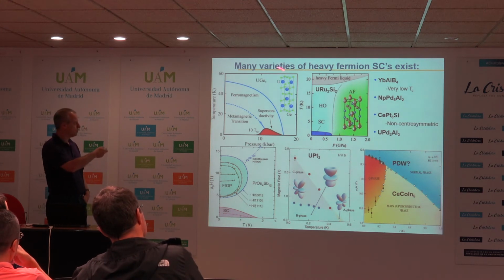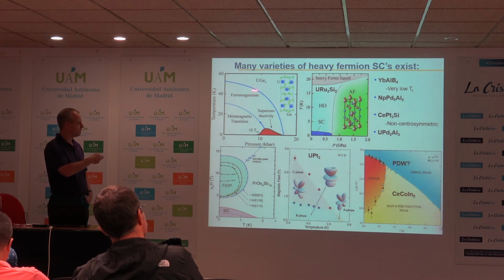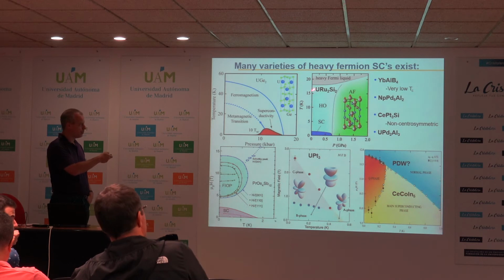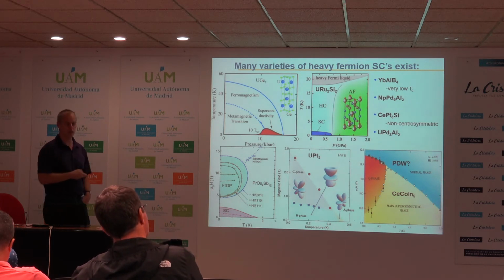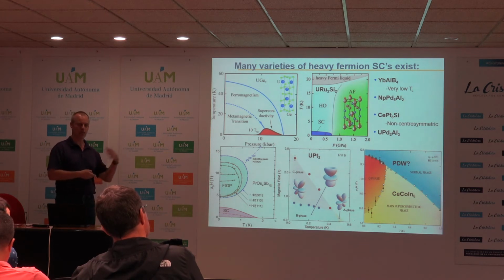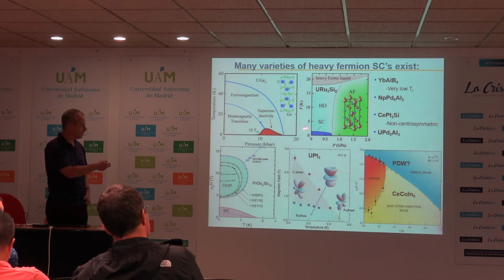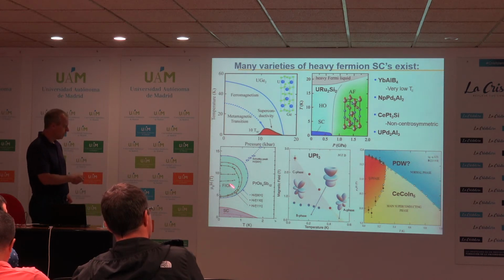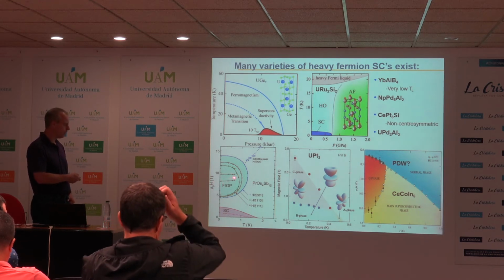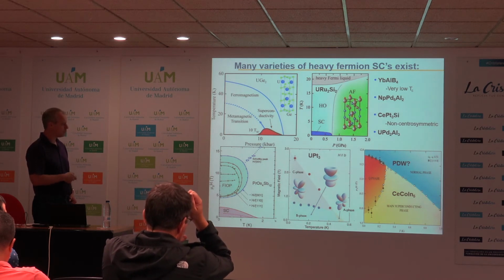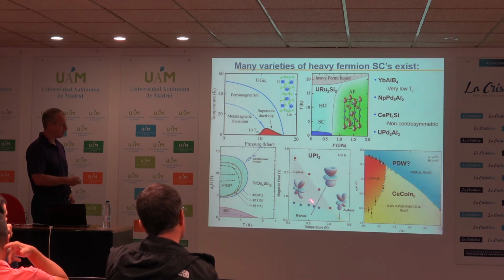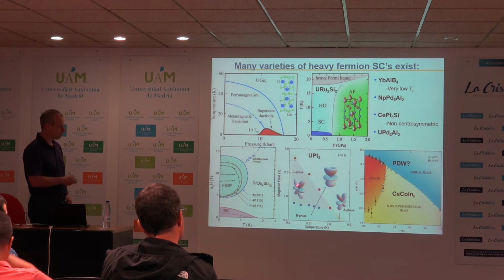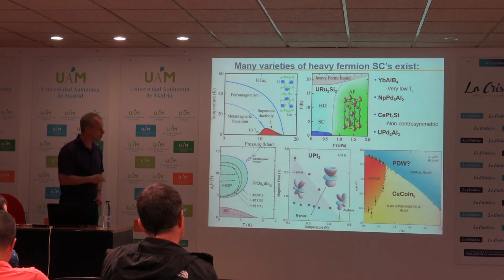So in the following talk, we'll hear about the ferromagnetic superconductors, systems like UGe2, where in this case, superconductivity lives within the ferromagnetism. But there are also cases like uranium-ruthenium-2-silicon-2, where we don't even know the nature of the ground state. So there's this hidden order state, which is highly debated as to what the order parameter of this broken symmetry state is. But the superconductivity seems to live only inside this hidden order state. As it becomes a nice antiferromagnet, in fact, the superconductivity is suppressed. Here's a praseodymium compound, which has quadrupolar ordering in an applied magnetic field. You find superconductivity here. UPt3, I already mentioned the three different phases that you find in UPt3, where quite different order parameters are expected in those three different phases.